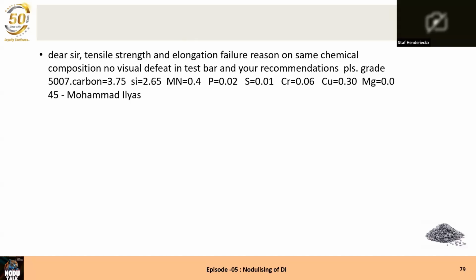Yeah. Let's say if you have once a good casting and once a bad casting, you did something different. If it's not the chemistry, there will be a difference in the chemistry, and look especially at the magnesium to sulfur ratio, that's already one. If there is a difference, the nodule count and the nodularity are very important.